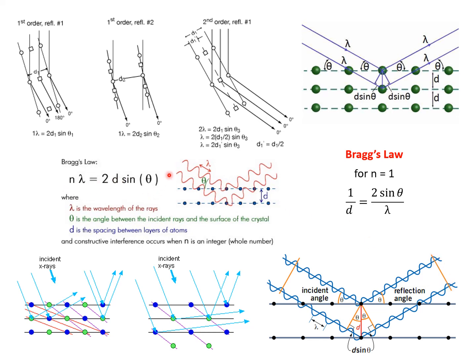In that case, that corresponds to the Bragg condition and Bragg's law, where the difference in the path length of this plane wave coming in and this plane wave exiting, this path length difference here, is given by 2d sine theta.